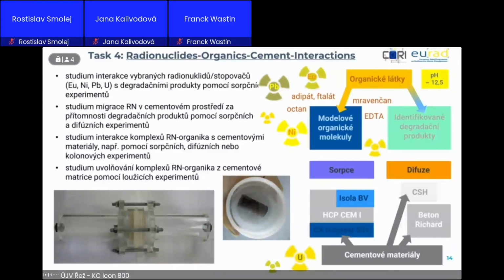or hydrolysis. We found that there are some phthalates, adipates, and some other compounds. In task 3, we found what is happening when I add cement matrix to the organic compounds, and task 4 was the result of all the investigations, where we try to find the migration of the radionuclides with or without organic compounds. The basic idea was that if I add an organic compound, for example phthalate, to uranium, it can be transported with higher velocity through the material.